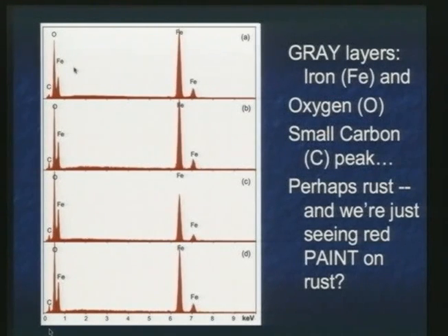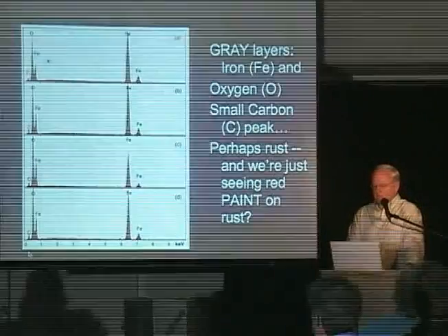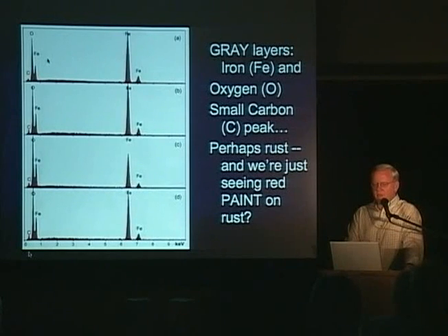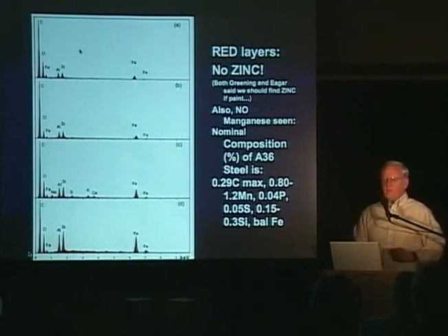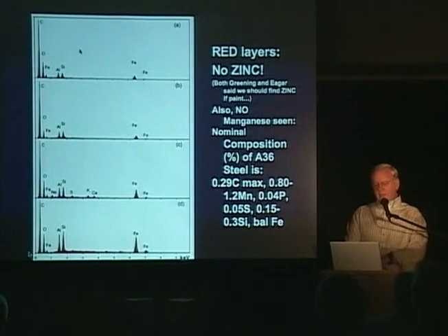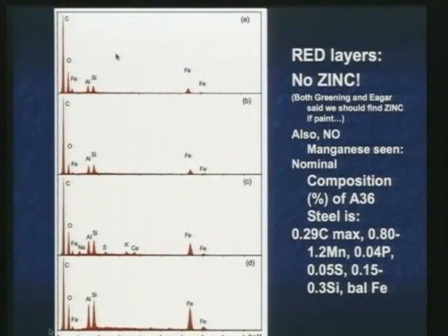At first we look at the gray layers, which show oxygen and iron very clearly, and a small carbon peak. The question arose, I had this question early on, perhaps what we're seeing is rust in the gray side, and the red is just paint, so we're going to check that hypothesis. We check very clearly. Looking at the red layers, there is no zinc, no manganese seen either. The nominal composition of A36 steel, as used in the World Trade Center towers, has about 0.8 to 1.2% manganese. So where's the manganese?